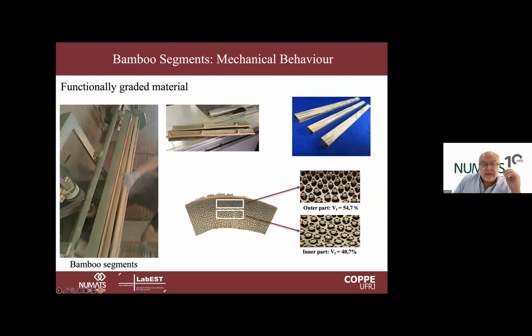So what we did here was to take strips from the part where we have a higher concentration of fibers, typically around 55% of fibers in this region. Normally, the fibers are all aligned. And then in the inner part, the concentration decreased to 40%, and this changed the properties of the strip.